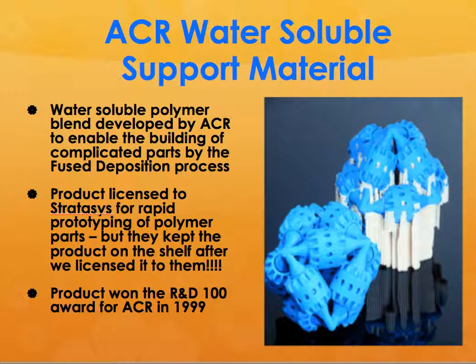And the other thing that we did at my previous place of employment was, because the fused deposition modeling needed some kind of support material at points where there are undercuts and overhangs and things like that, we developed a water soluble material that could be deposited with a second nozzle. And this is the actual part itself, and then you can just wash out with cold tap water. And this product won the R&D 100 award for my old company in 1999.